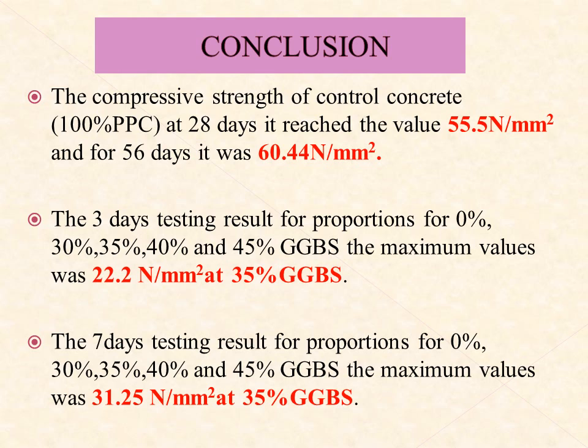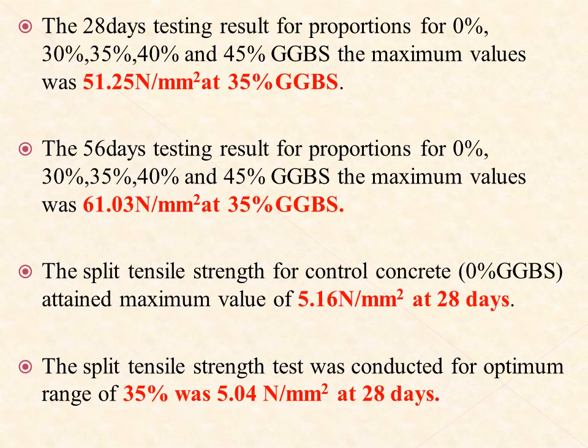The 3 days testing results for proportions of 0, 30, 35, 40, 45% GGBS show the maximum value at 35%, which is 22.2 N/mm². Then the 7 days test, 28 days testing, 56 days testing, and split tensile strength. For control concrete with 0% GGBS, a maximum value of 5.16 N/mm² was attained at 28 days. The split tensile strength conducted for the optimum range of 35% was 5.04 Newton per mm².